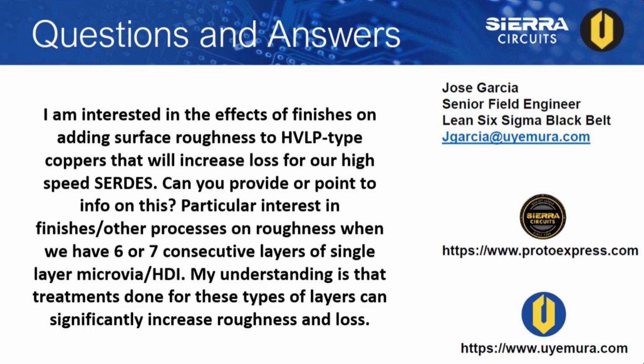I have some comments on this because we look at this every day. So he's primarily talking about roughness on inner layers. So you have very low profile copper foil. It has a dendrite structure on one side of it, and that's what the very low profile is. Then you also have the alternative oxide adhesion promoter that we put on the smooth side of the copper prior to lamination. So both of those have an impact.